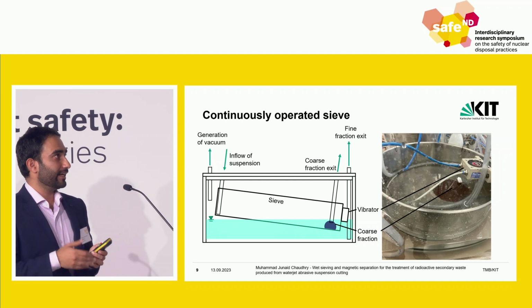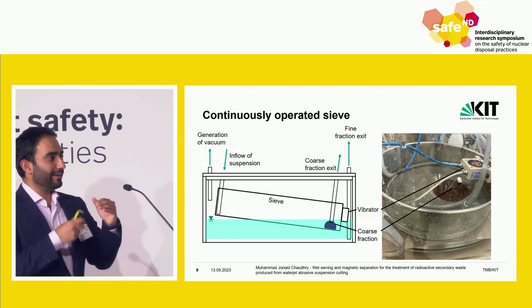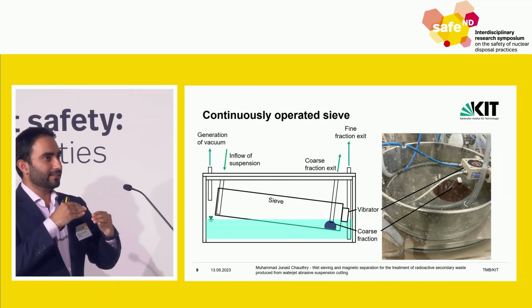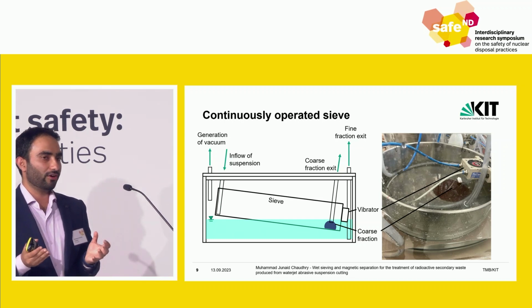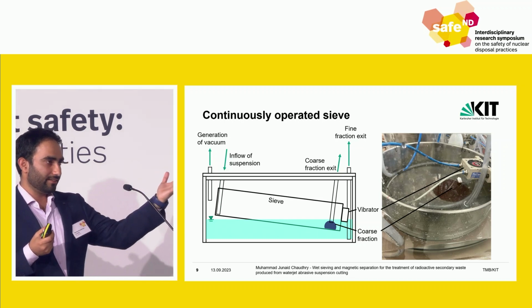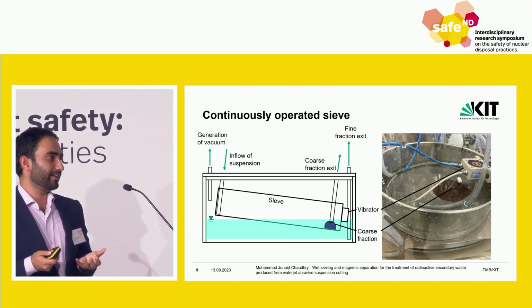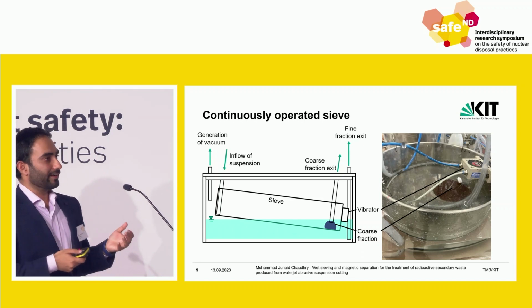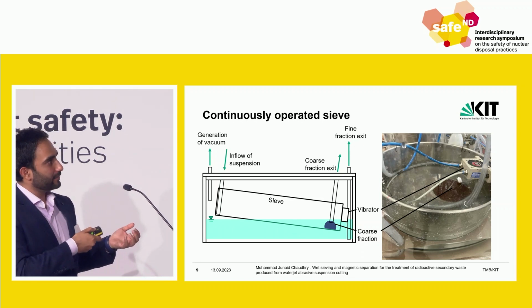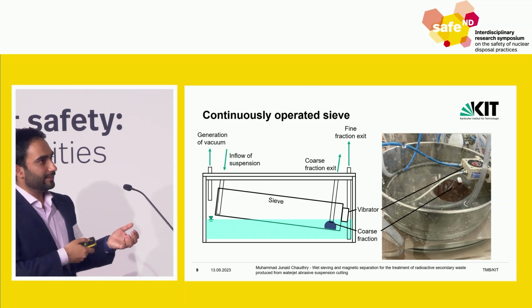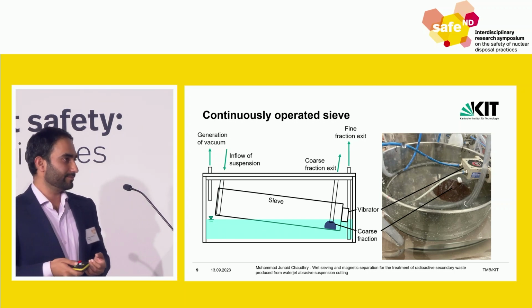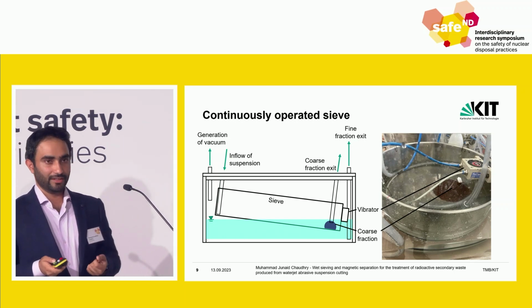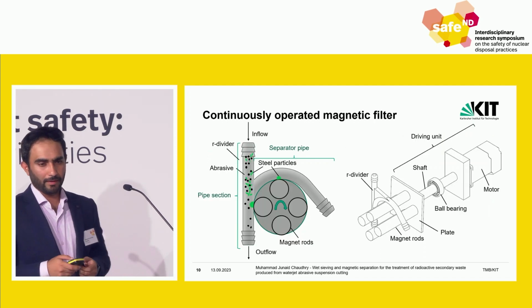This shows that the particles we really want to separate have only about 4% error shown by this continuously operated sieve. For example, for only one pass through this, there is only a 4% error, and it's quite remarkable for this developed sieve.